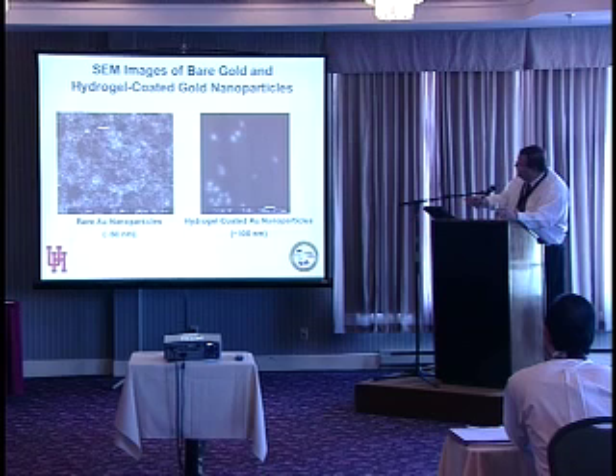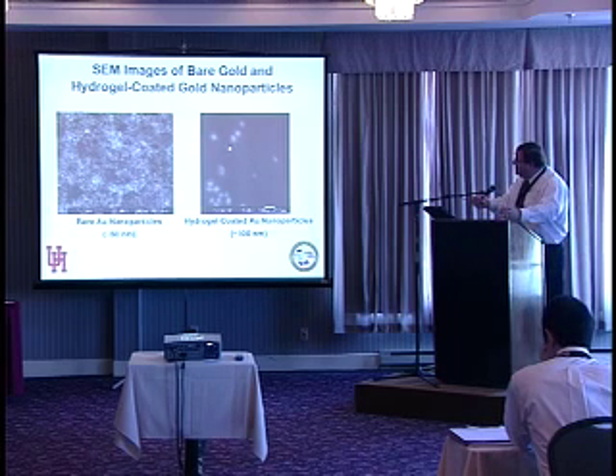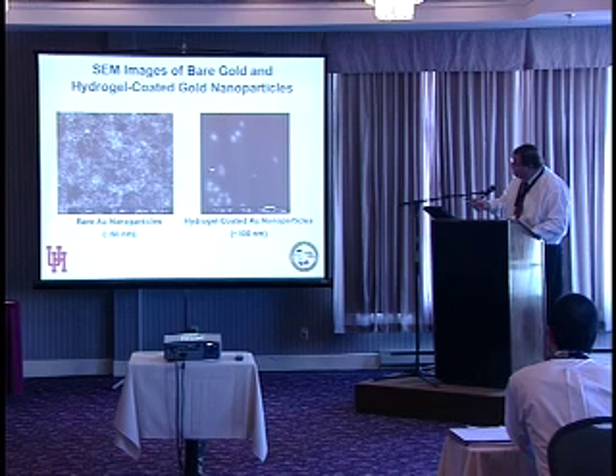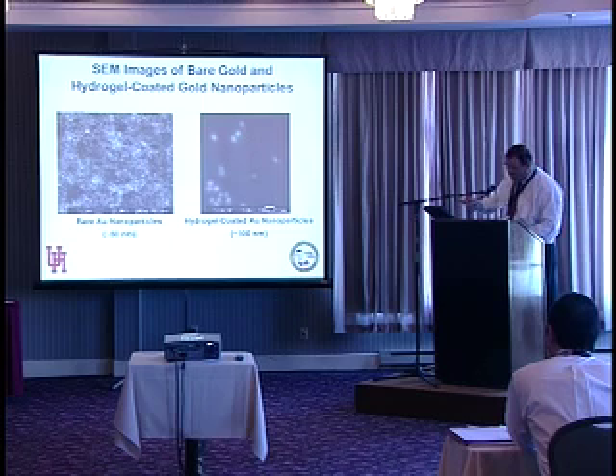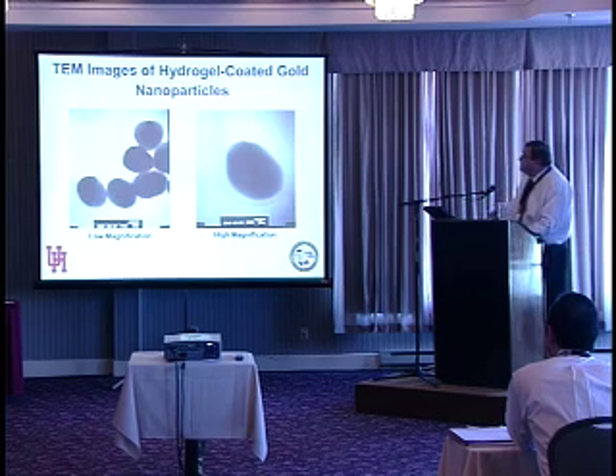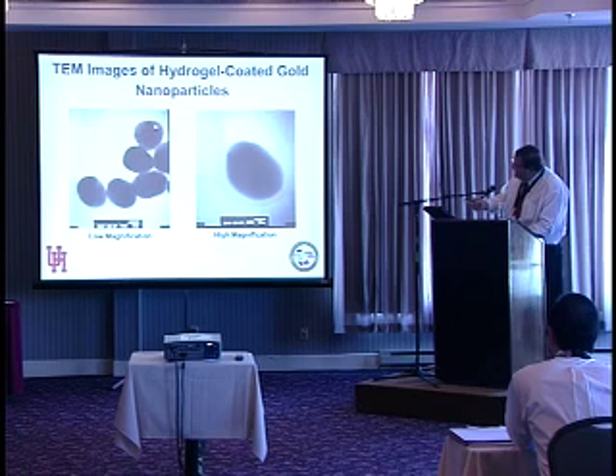It's not real clear here, but these are just simple gold nanoparticles with no coating. And here are some of the hydrogel-coated gold nanoparticles. You can see they have this little outer coating on the outside. That's the hydrogel coating on the nanoshells. Some TEM images of them. Again, here is the gold particle, and you can see just on the edge, you can see this hydrogel coating, and here's a magnification. You can see the hydrogel around here.